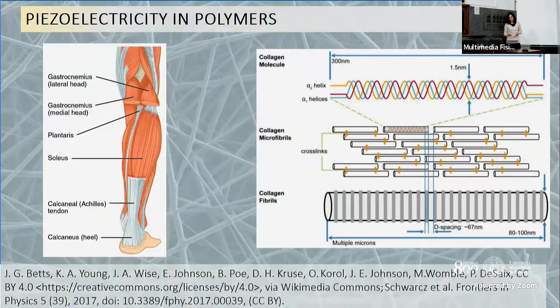Piezoelectricity has also been demonstrated in Achilles tendons, and Achilles tendons are mainly constituted by type 1 collagen molecules, which is one of the most abundant proteins in humans. And collagen molecules are in the shape of a triple helix of amino acids, and they are again arranged in a very ordered form, and they form microfibrils, which are again arranged in an ordered way to form fibrils. And also collagen is piezoelectric. One idea is that the presence of hydrogen atoms on the helix enables the establishment of a piezo potential, so the formation of electrical charges which form a dipole upon deformation.